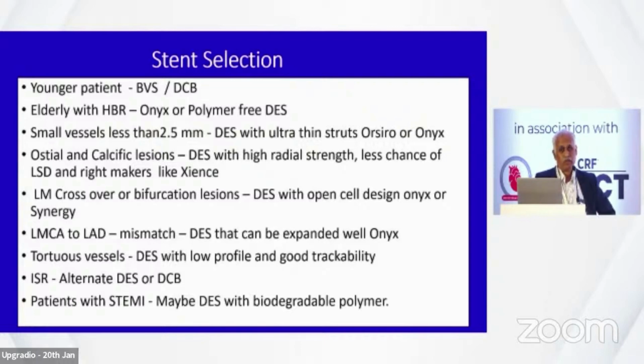If you're putting a stent from LMCA to LAD, sometimes there's a significant mismatch. You have a 5 millimeter LMCA and a 3.5 millimeter LAD or 3.5 circumflex. Your stent should have good expandability. Onyx is one of the good stents. Again, for trackability, you should have ultra thin struts.